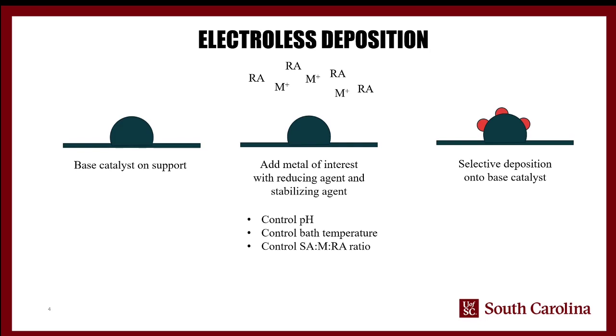So if you had just, say, carbon, you're not really going to control where everything deposits, and so you'll end up with larger particles and probably fewer of them. With this base catalyst, you can spread them out, and you can ensure that you end up with uniform distribution of these particles all across your catalyst substrate. And the general process here is you need to control three things. You need to control your pH, you need to control the temperature of the chemical bath, and you need to control the ratio between your stabilizing agent, your metal precursor, whatever it might be, and your reducing agent.